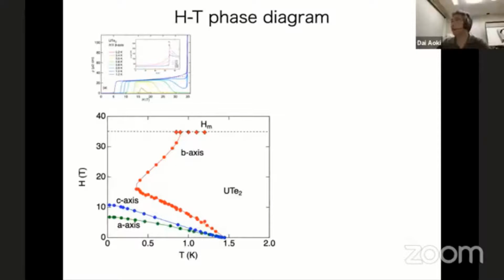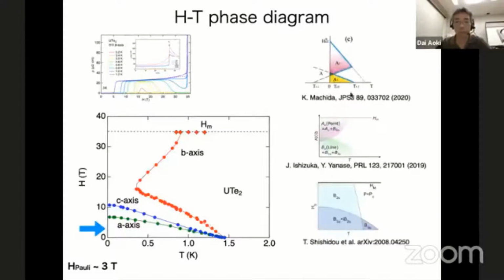From TC, the Pauli limiting field is only 3 Tesla. So all directions highly exceed the Pauli limit. So it also indicates the spin triplet state. And from this strange B-axis HC2 curve, many theorists also have interest, and Professor Machida, Yanase and Shishido propose several different parameters, but these differ from each other. So I think it's still an open question.